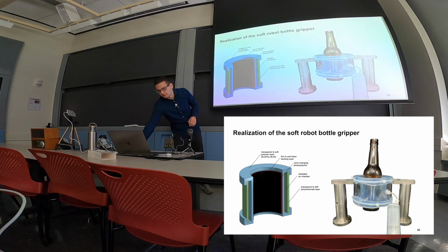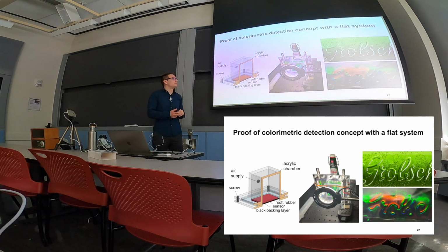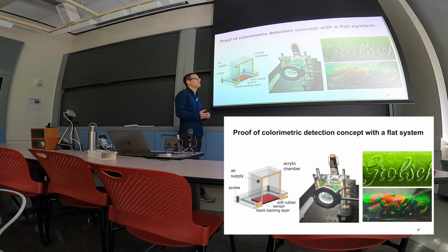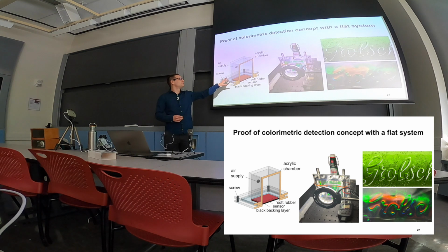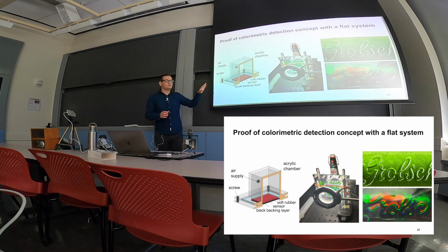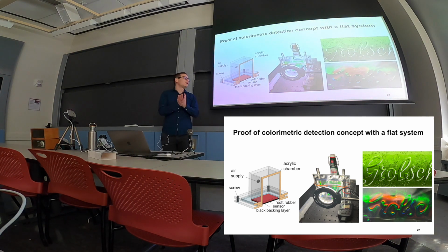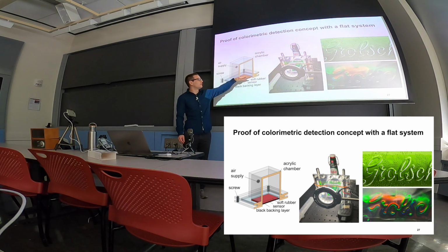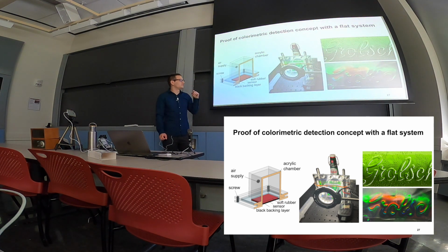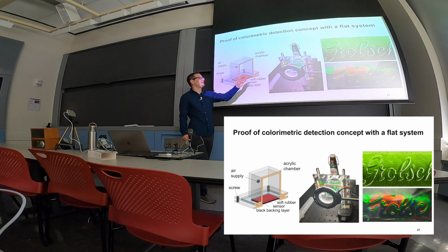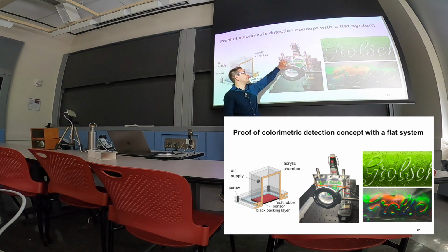And to not only verify that I was able to lift up a bottle, but also that I could detect those textures, and since I wanted to make my life a little bit easier, I reproduced the system in a flat-shaped form, so I just used the layer without being attached at the ends and pressed it between two acrylic tubes, and placed it over one side of a hollow die that I could also inflate, to have a system where I could press this color-changing material with the soft robotic material against anything like the bottle in the setup that we can see here in the middle part.